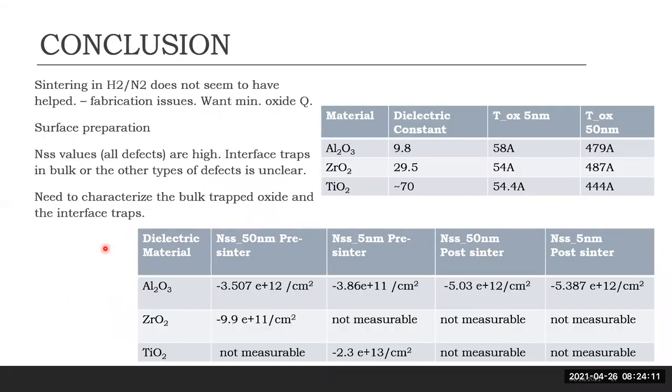While the next natural step is to stack these layers using different materials and thicknesses for each of the functions, there are some effects observed in this preliminary experiment that may need looking into. The data on the zirconium and titanium oxides indicate that the effect of annealing in forming gas, and perhaps of annealing itself, on the layers individually may need its own experiment. Since there was an issue with the deposition of zirconia, it is possible the standard RCA clean was insufficient to optimize the surface of the wafer for the process.